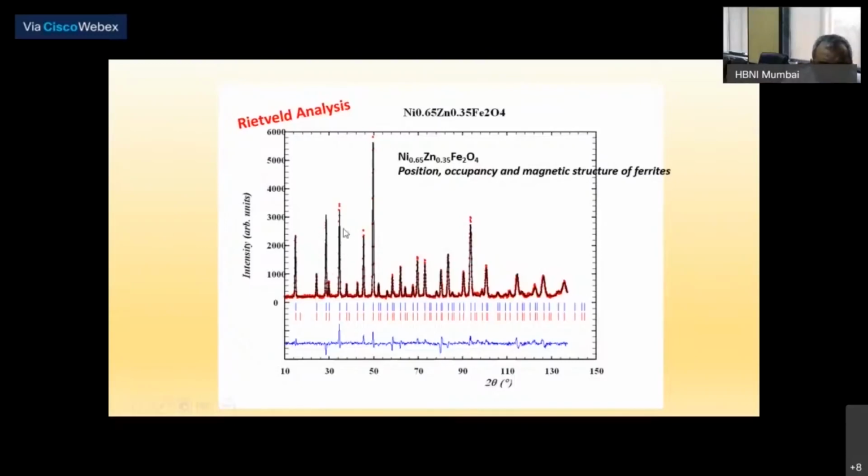I have the experimental data and I start with a model of my ordered crystal. I start with some site moment for the magnetic sites, and then generate a Fourier inversion of that, generate this experimental data and compare them. After that, it is like any other data fitting technique, a chi-square minimization. And this chi-square minimization goes on, and you can see this is the final result.